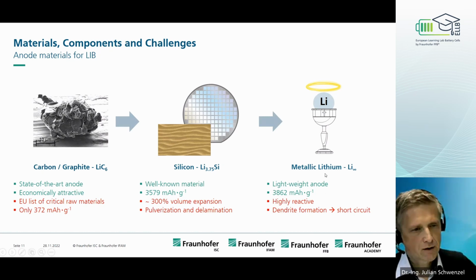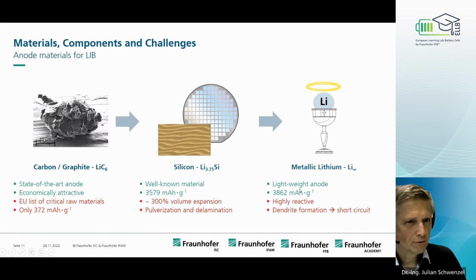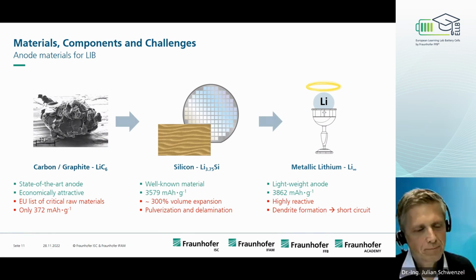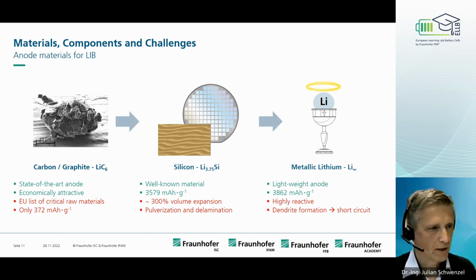And finally, the holy grail is to use really pure lithium metal because it's very light and has a high capacity, but pure lithium is very reactive and can form dendrites, and this will also be critical to handle because of short-circuiting. So this is really the holy grail for the lithium metal to use here. But this is really a problem, how to handle the reactivity and the dendrite formation.